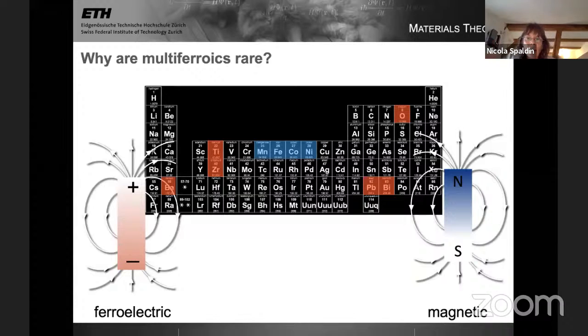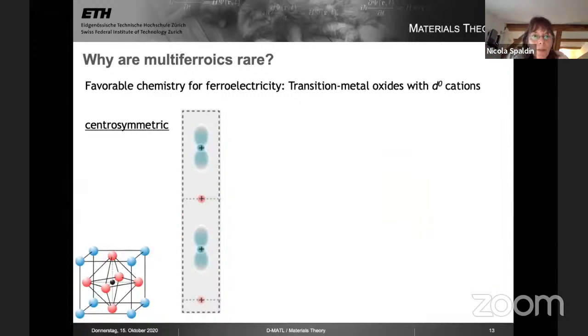I'm going to try and explain to you why from two sides. I'll start with a hand-wavy chemical bonding picture for those of you who like to think about where electrons go in solids, and then I'll show you the perturbation theory approach. Okay, so the favorable chemistry to be a ferroelectric is that one should be a transition metal oxide, but your cation should be a d0 cation. So it should be in an oxidation state such that it's given up its d electrons. This is an observation: most of the standard conventional ferroelectrics are transition metal oxides with d0 cations. They have empty transition metal d states.